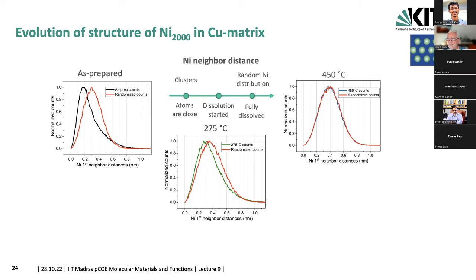Yeah, so we have a very clean, obviously, surface also. Once the temperature becomes high enough, nickel and copper start to interdiffuse. And roughly, this is also what an extrapolated diffusion coefficient from higher temperature would tell you. In this range of temperatures, this is what should happen.